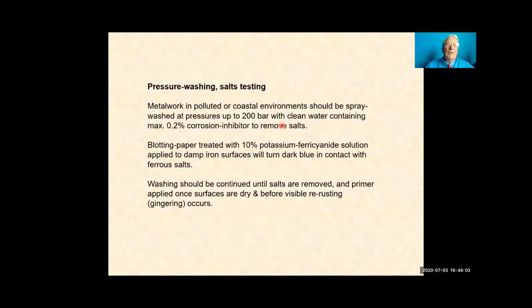In polluted environments, it's a good idea to do pressure washing with pressure up to about 200 bar, again with the corrosion inhibitor in it. And then there's a process for testing for ferrous salts using 10% potassium ferricyanide. You have a 10% solution, you put it into blotting paper, you let it dry, and then you take it out on site, and after the blasting, you dampen the paper, just put it onto the surface, and if there's any ferrous salts, only ferrous salts, it will turn